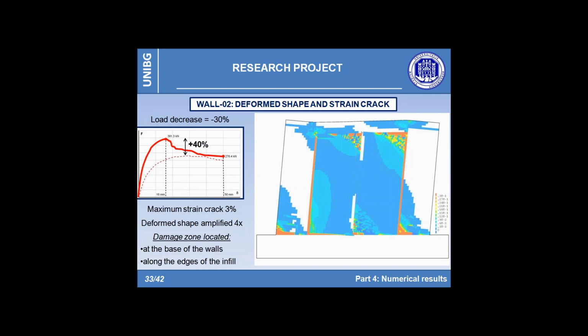The infill panel presents a crack pattern that appears similar between the two halves. This is due to the presence of the elastic interface with no stiffness model along the center line, which permits the two substructures to behave as independent parts. Moreover, it can be seen how once the central panel becomes inactive, most of the externally imposed loading action affects only the structures composing the frame.